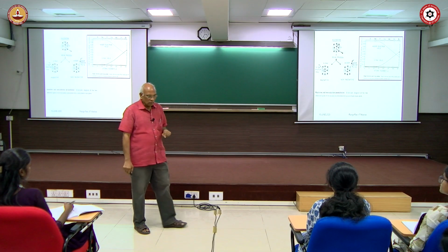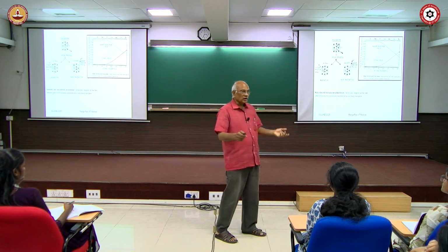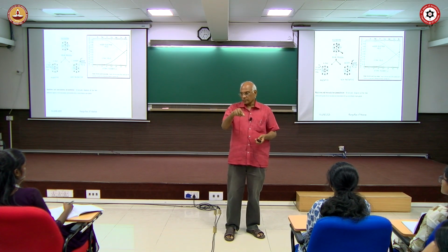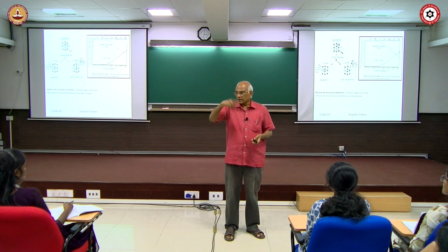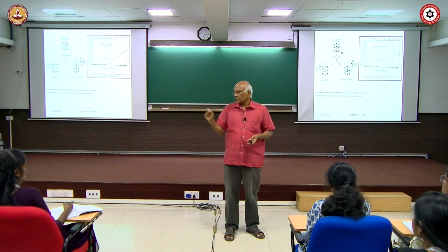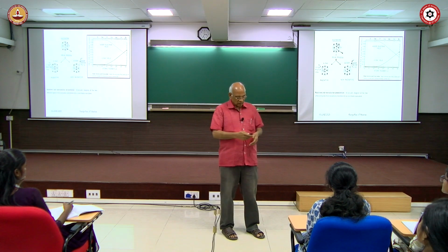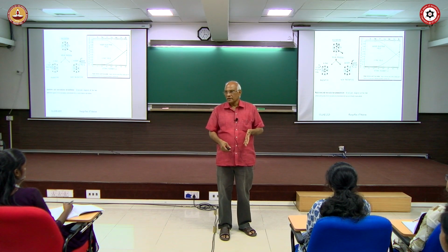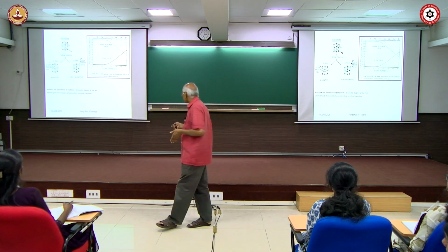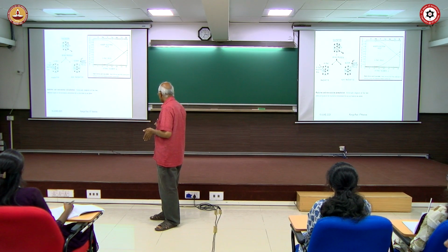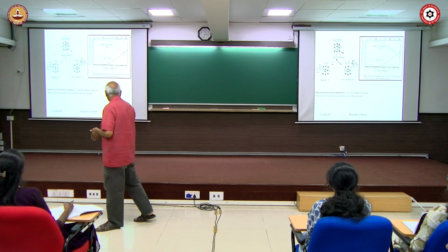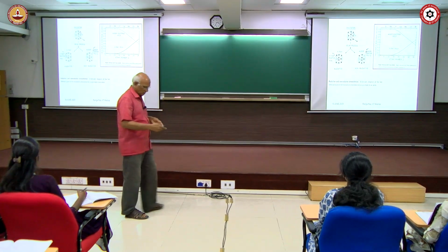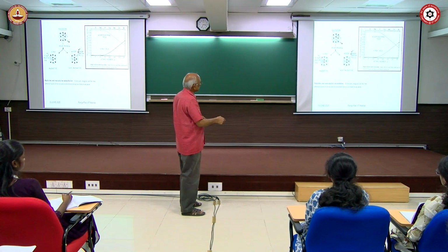So what people normally do is to use Auger spectroscopy to find out the contamination of the samples by oxygen, carbon contamination. They record the Auger, because the yield is very high. So even if a small amount of carbon, oxygen, or any other contamination of the lower atomic number elements is present, they can clearly see that. This is an experimental curve, basically drawn by doing experiments on various elements. So these are the two decay processes that you should remember.